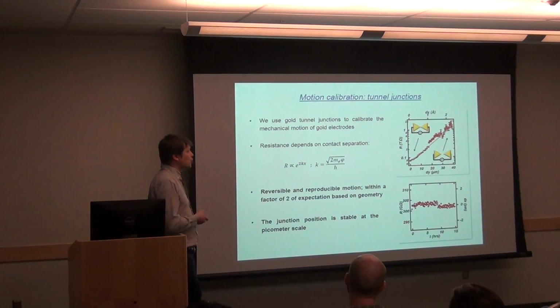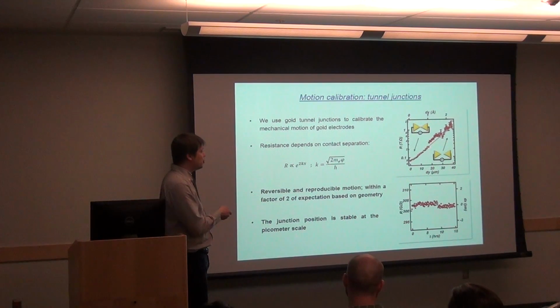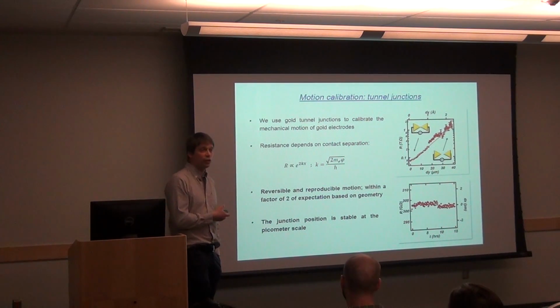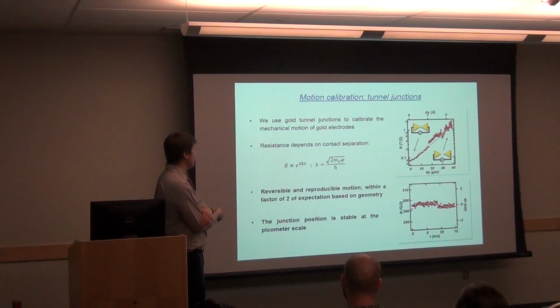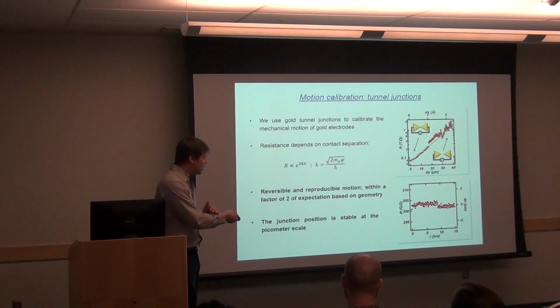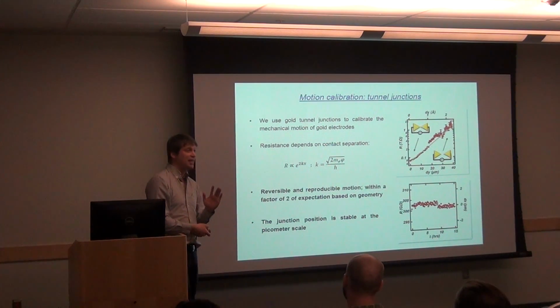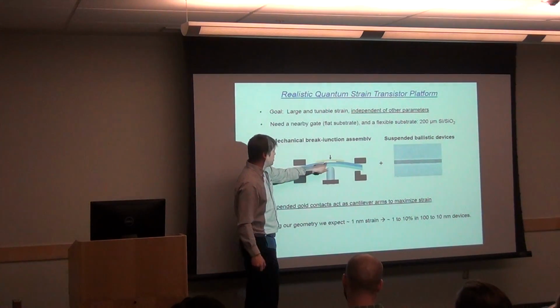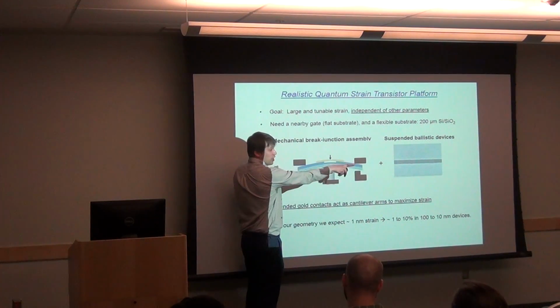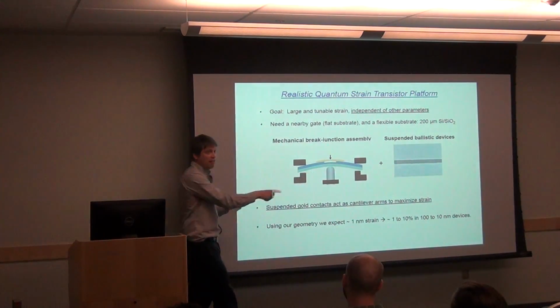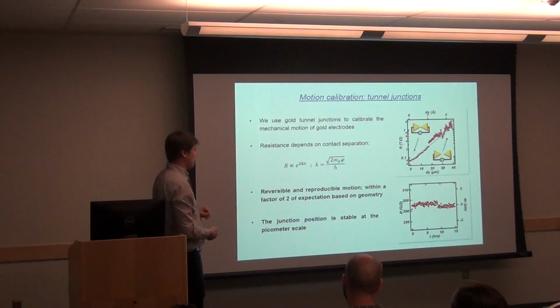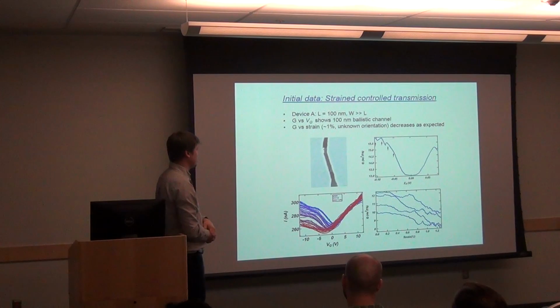Now, to make sure the motion works well, what we did is calibration with just tunnel junction. So we use gold tunnel junction, and just the electron flow across a vacuum gap is exponential with displacement. So with this exponential, we can do a very good fit and actually see that the motion is very smooth, and also that it's extremely stable. If you just park at one position for the motor and you wait, you get basically stability that's order of much less than 1 picometer. Okay? It sounds crazy, but why it's so stable is because you're pushing this way, but you're stretching this way. So you have a huge reduction factor in any vibration from this sort of lever construct. So that's important to us because we want very stable experiments.